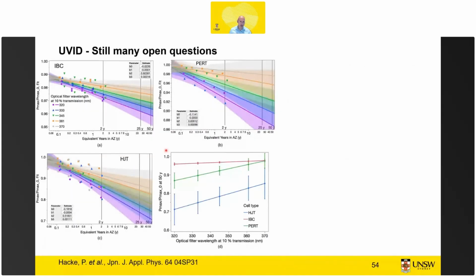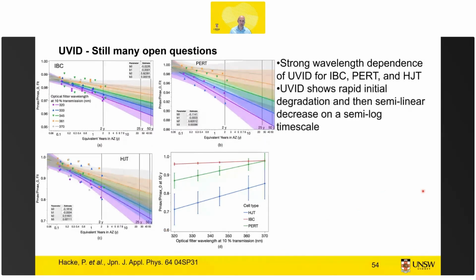And so the good news is that this dark storage degradation is not relevant for field application. Then again, work from NREL showing the different impact of wavelengths on the performance. So here it's the performance extrapolated in a semi-logarithmic plot in equivalent years in Arizona. The good news is that IBC, PERT, which has the same front as TOPCon, and heterojunction, IBC in this case was very stable, not always. We have definitely seen results in the lab when you take away the front surface field that it's not as stable. But PERT, degradation at 30 equivalent years is a little over 10%. Heterojunction is a little bit stronger, but overall it's not as bad for these tested samples.